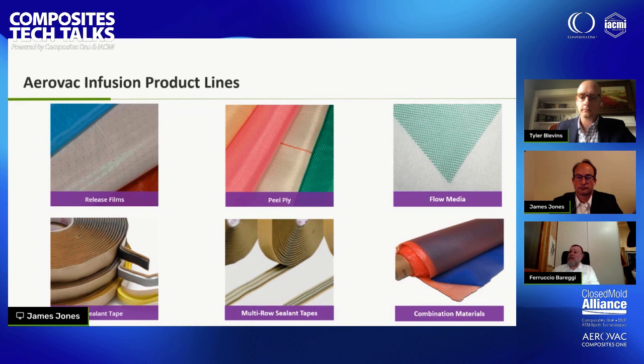An important part of the job that the combination material does is not only the fact that it's easier and faster to put in place, but also the fact that when you overlap a combined material, you are not perturbing any flow of the resin, because you always have the mesh between the two release films. While if you simply overlap perforated release film, it's very difficult for the holes to match. So you are generating a kind of stop for the resin flow that may perturb the flow of the resin along the part.